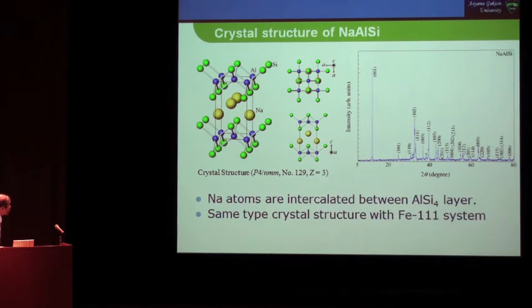By developing this idea, we try to get sodium aluminum silicon instead of calcium aluminum silicon. But sodium aluminum silicon has a very different crystal structure. After that, we noticed that this aluminum silicon layer is very similar to the so-called iron 111 system.